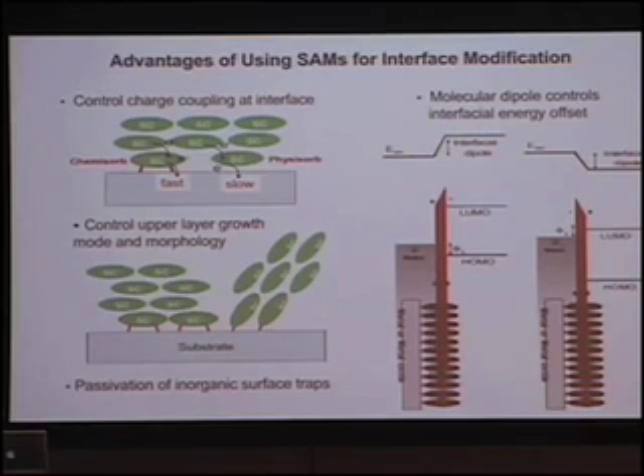We utilize SAM to provide several different functions. When you have a SAM to coat, for example, a substrate with a metal oxide electrode, you can control the charge coupling at the interface, depending on the shape and also the energy of the molecule you covalently bond on the substrate. You can use that to nucleate the growth of the top layer, so you can get much better control of the morphology with a much better conducting path.